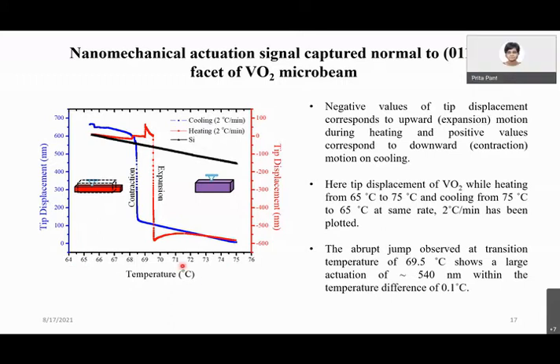And when the contraction happens during cooling, the tip is still in contact with the sample? I mean, somebody is monitoring that the load doesn't drop suddenly. You are right, it did actually drop. In fact, the cooling experiment is much more difficult because there is a definite chance of the tip getting disengaged.